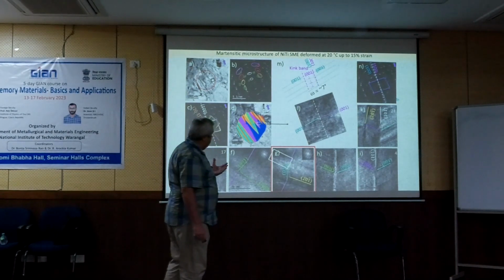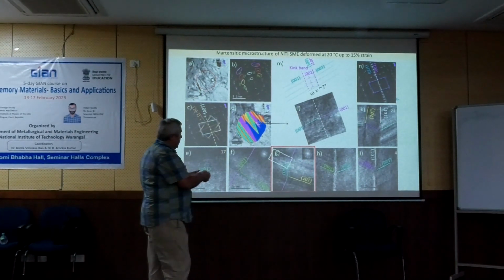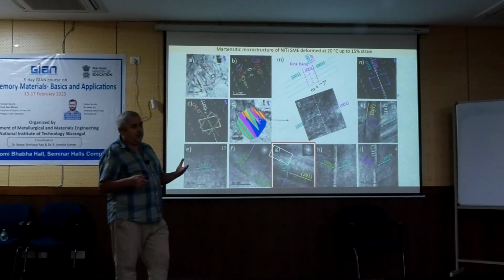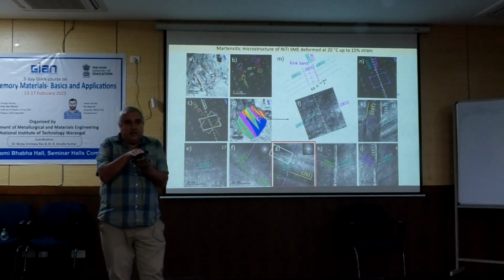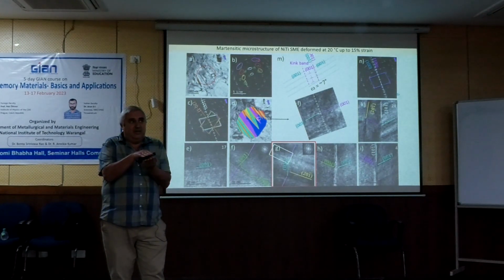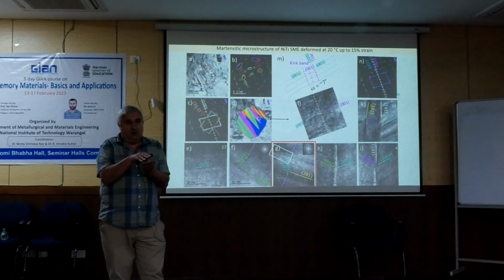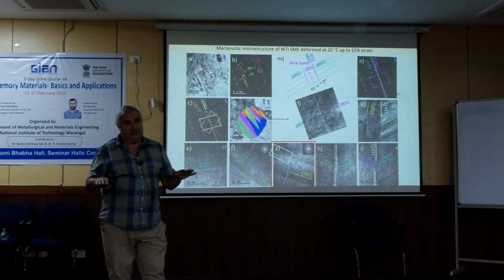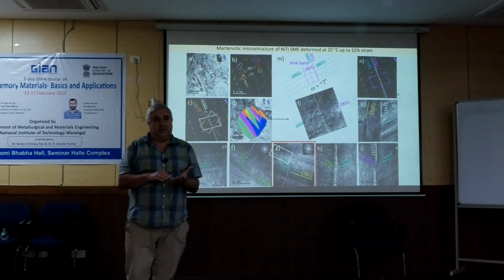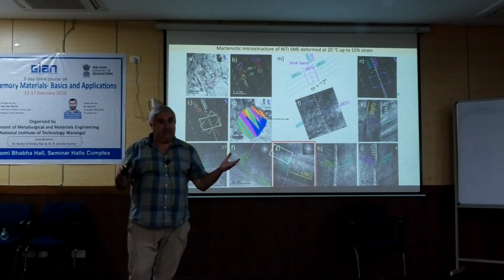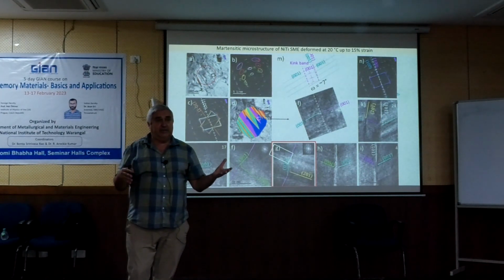Okay, and then I should say this is a martensite which is monoclinic, and the monoclinic lattice is very anisotropic in a sense that the only dislocation slip which can occur is in this basal plane (001) in the [100] direction. There is no other way it can deform by dislocation slip, and this is common to some geological materials which are also low symmetry materials.